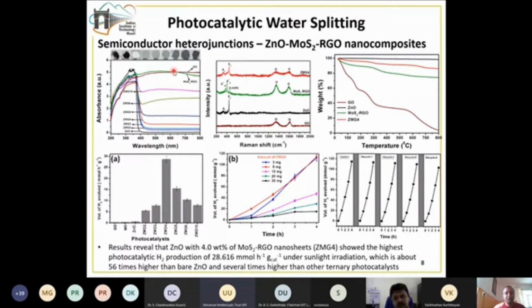We also could see it from the color of the samples, because color is a kind of first indication. It's not the final indication. Like sugar and salt, both are white in color, but they have completely different properties. But at least we can get some information from the color of the sample. So the GO, the MoS2 and the RGO are black in color. Zinc oxide is fully white in color, and the different nanocomposites are in different shades of gray, which you can see.